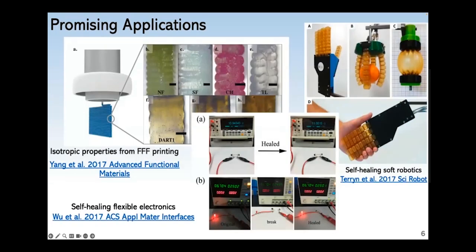First, I want to be a little optimistic and discuss some of the more promising applications with these materials. So, in this top left set of images are some conventional fused filament fabrication resins. And then down here is a DA resin. And one of the major challenges I see in 3D printing that Diels-Alder materials avoid is this interlayer adhesion. In many cases, 3D printed materials are considerably weaker in the print direction because the adhesion isn't strong between the layers.